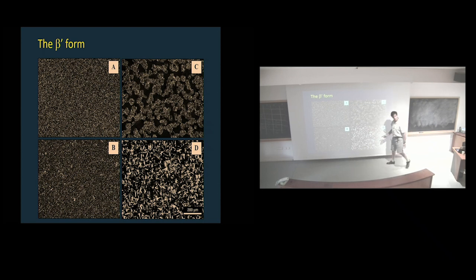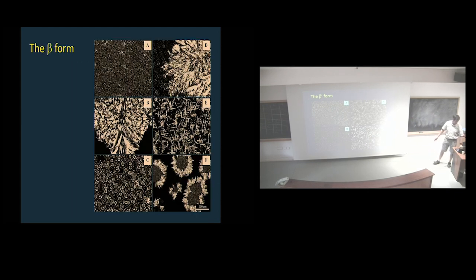But look at the microstructure difference between all of these. All of them are beta prime. So it depends on how you got to the beta prime. That's sometimes, did you cool it, heat it, beat it up, kick it? What did you do to it? Cool it down again, and you get a different microstructure. And look at this. You can actually have a very fine-grained triclinic if you cool it and stabilize it, as opposed to you let it do whatever, you get sunflowers. You know, you can get all of this. So this was actually a good point to make: don't trust what you see under the polarized light microscope and call it something.